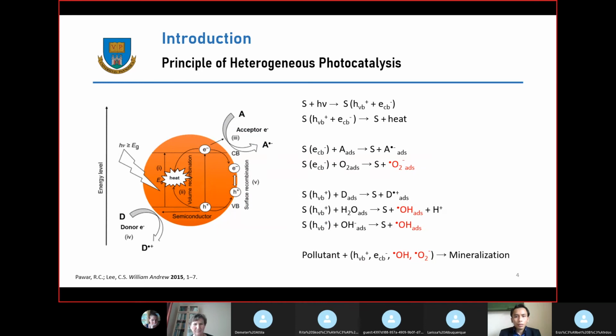So this is the general reaction of heterogeneous photocatalysis, when the semiconductor or catalyst is illuminated by light, the electron and hole are produced and migrate to the surface of the catalyst. But at the same time, these charge carriers may recombine with each other, both inside or on the surface of the catalyst. So the electron on the surface of the catalyst can react with oxygen to a superoxide anion radical, and the hole reacts with water producing hydroxyl radical. These active species then attack the pollutant for the mineralization process.